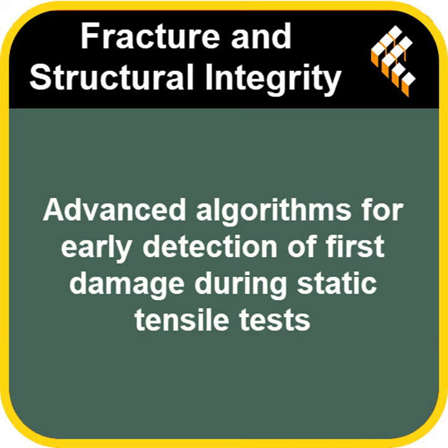Okay, that sounds incredibly solid in theory, but the proof is in the pudding, right? How well did this algorithm actually do when they tested it on real materials? The results were really compelling. They tested it against the established RTM method, the cyclical fatigue one we talked about earlier, using the same materials. They used a couple of advanced plastics, nylon CF, and a PA12 from multi-jet fusion, and also a common stainless steel, AISI 316L. A good mix.